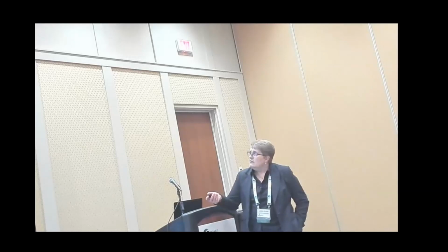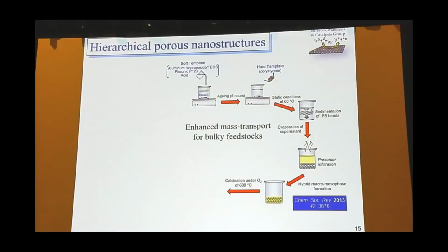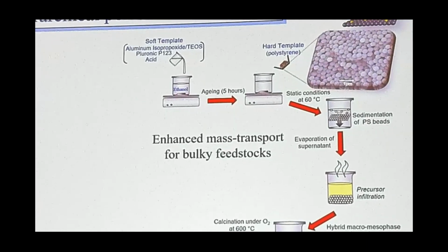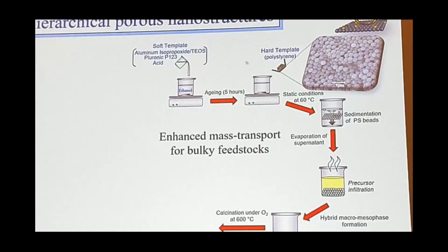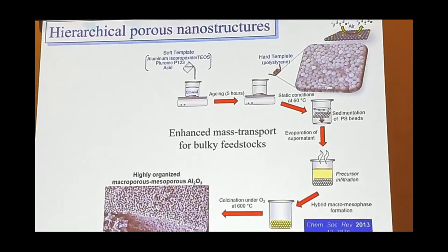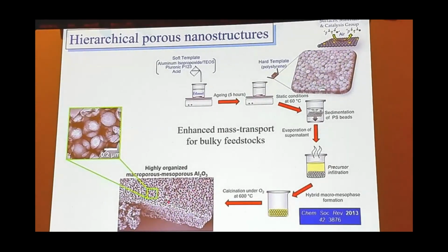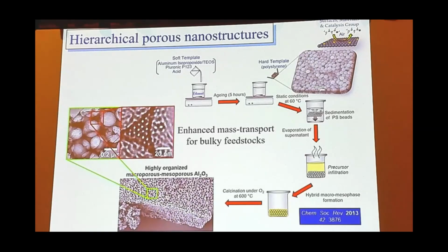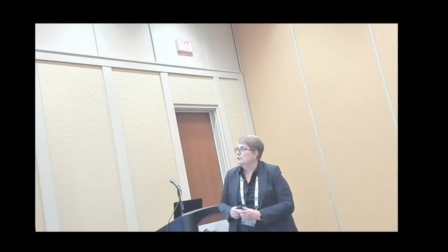And the way we've been doing this is to develop hierarchical porous structures in which you start off with your conventional SBA-15 like templating solution with Pluronic surfactants. But then you add to this a hard template, which is typically polystyrene nanospheres that can vary over the range, maybe 100 up to 600 nanometers. And then you process the material, and then ultimately you end up with these monolithic structures that have large voids where the polystyrene is. And then if you look at the walls, you can see the mesopores where the Pluronic surfactant is templated. So these systems, by punching these big holes in the long 2D network of SBA-15, enable basically improved mass transport.